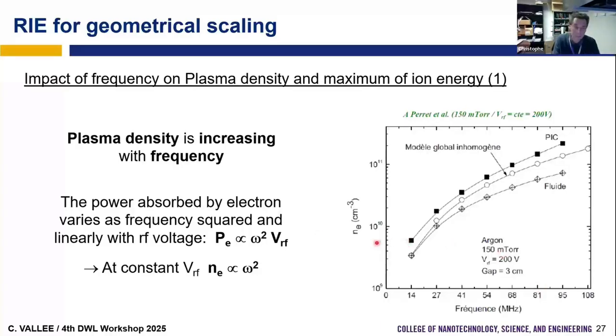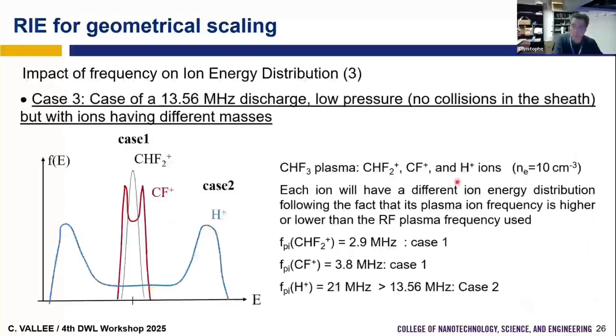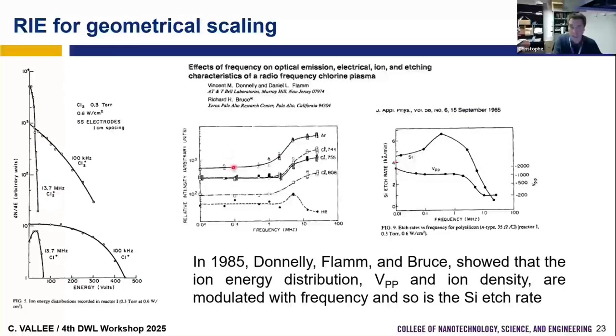So what we can say is that the power absorbed by electrons is found to be proportional to the square of the frequency and varies linearly with the RF voltage. So for a constant RF voltage, for example, the plasma density, which is proportional to this number, will probably increase like the square of the frequency of the generator. So if you increase the frequency of the generator, you increase the plasma density, so you increase the ion flux. And so we go back to what was observed.